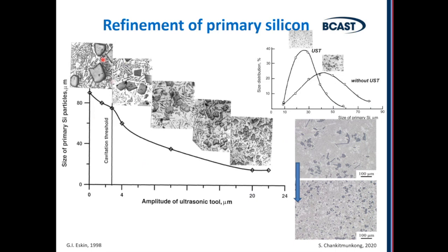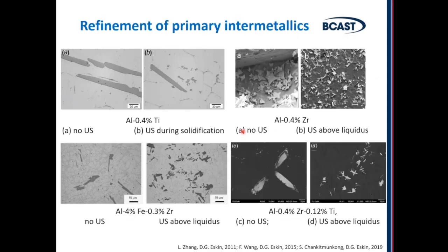This is an example of aluminum silicon hypereutectic alloys, piston alloys, usually 12 to 18% of silicon. So very efficient refinement of primary silicon. Also primary intermetallics of other origins, aluminum 3 titanium, aluminum 3 zirconium, aluminum 3 iron, can be efficiently refined. And by refining intermetallics in hypereutectic aluminum alloys, you can achieve a structure which allows these alloys to be used. Because, of course, alloys with such intermetallics cannot be used if the ductility is almost zero and fracture toughness is very low. But if you refine these intermetallics, you can actually start to use these alloys.